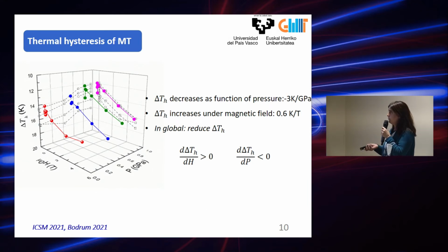Okay, another problem of these compounds is the thermal hysteresis. So we also studied what is the influence of pressure and magnetic field on this hysteresis, and we see that in the case of the pressure, the hysteresis decreases, so it's a good option, apply pressure. But in the case of the magnetic field, there is an increment of this hysteresis. But in total, if we play with both parameters, we get a total reduction of this hysteresis.